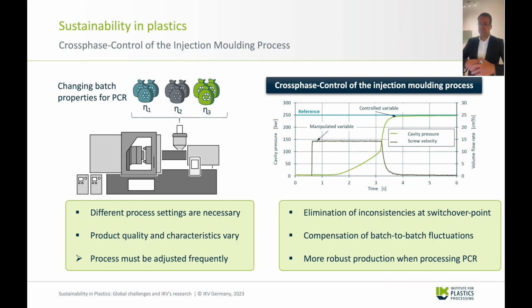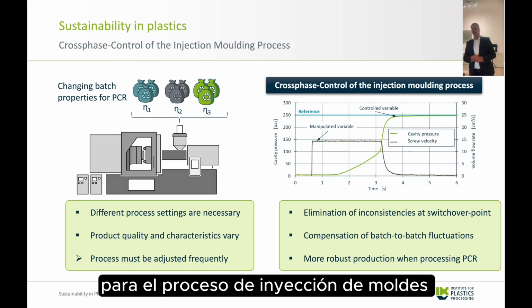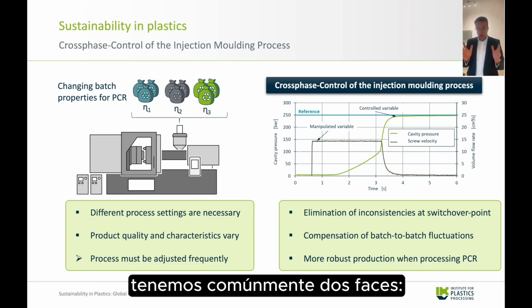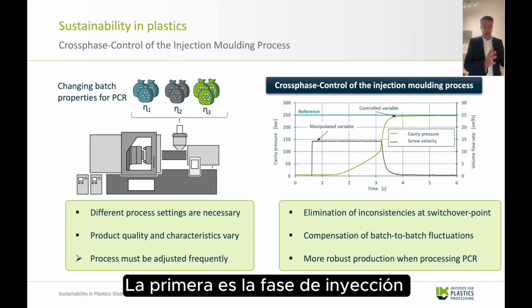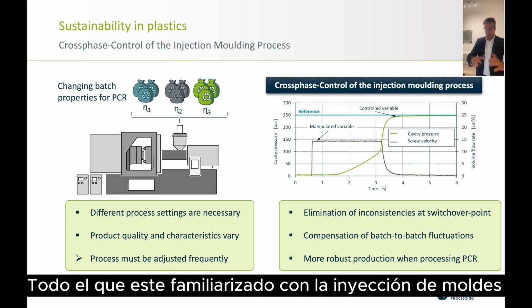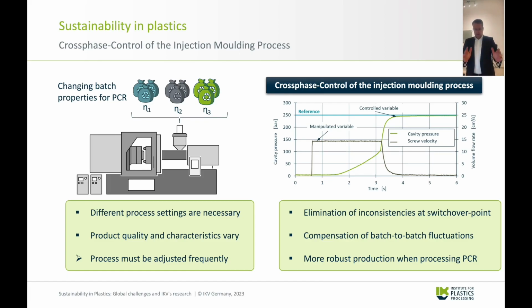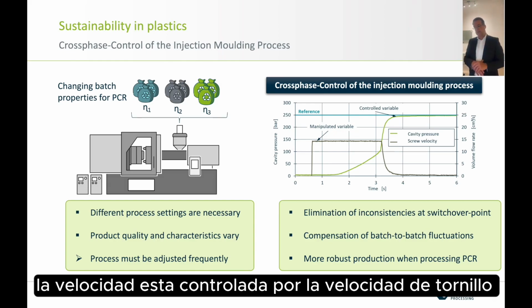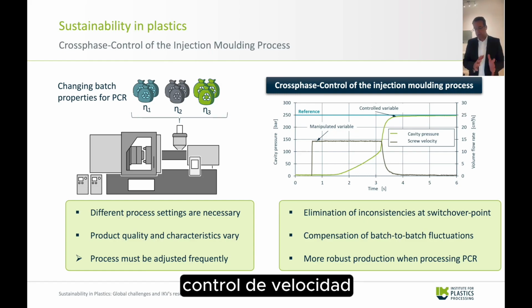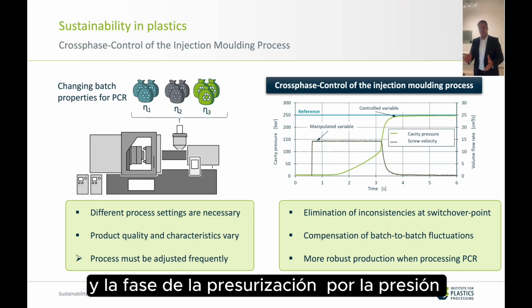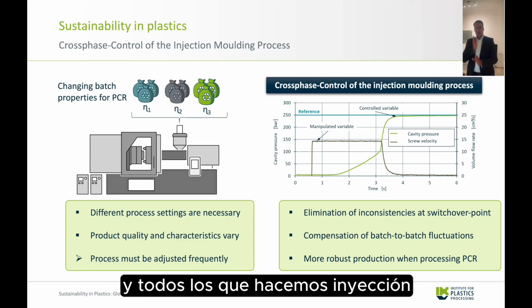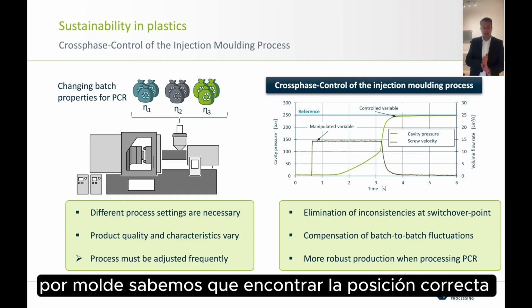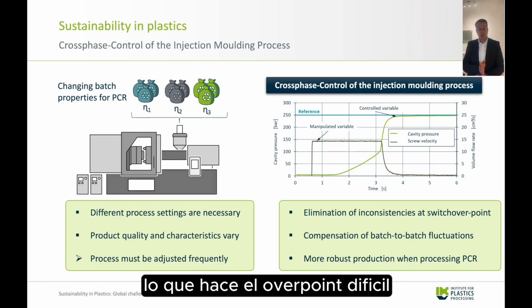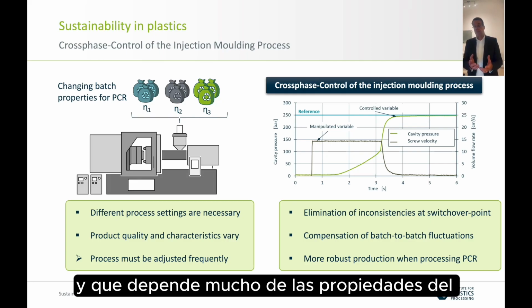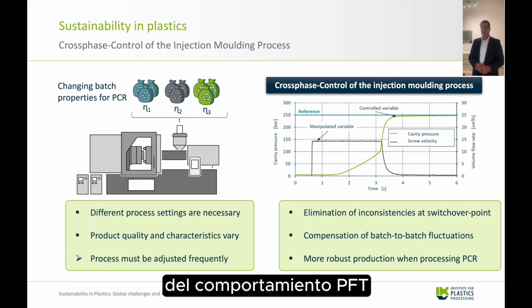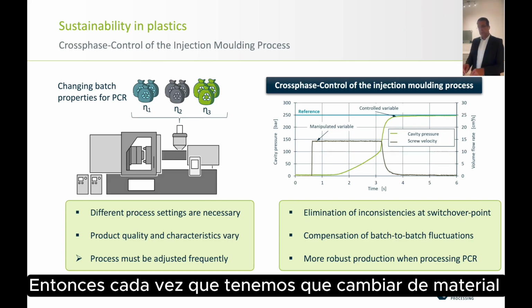And we develop what we call a cross-phase control methodology for the injection molding process. In the injection molding, we have usually two phases. The first is the injection phase. The second one is the holding pressure phase. Everybody who is familiar with injection molding knows it pretty well. In injection phase, the screw is controlled by the screw speed, and in the holding pressure phase it is pressure controlled. And then in between, we have a switch over point. And everybody who does injection molding knows that finding the right position for the switch over point is difficult. And it depends very much on the property of the polymer, on the viscosity, on the PVT behavior, and so on. So every time we change the material, we need to change the process.